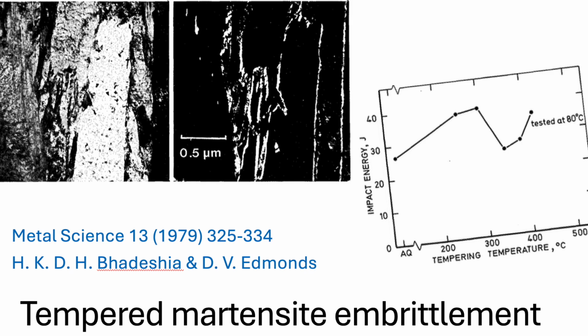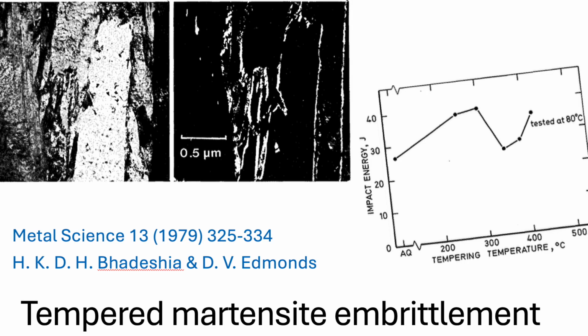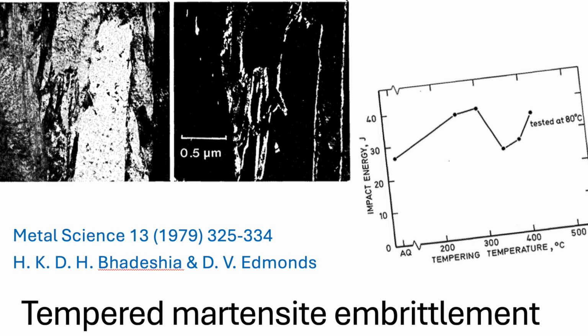Interesting. And interestingly, they also noted that an earlier stage carbide, sometimes called epsilon carbide, was not the problem here. It was the formation of the more stable cementite phase that proved destructive in this case. That really is a beautiful piece of metallurgical detective work. Okay, let's talk about the final act then, the actual fracture. How does that microscopic cementite film translate into a large catastrophic failure when the steel actually breaks under load?